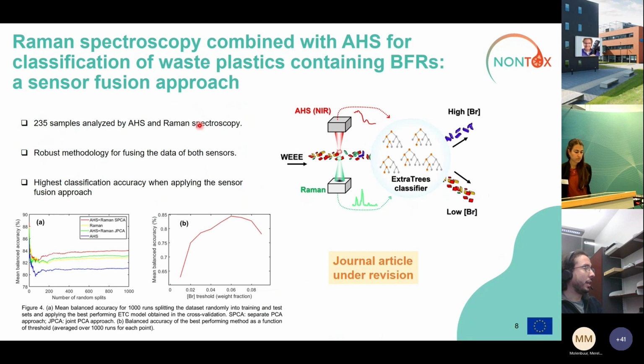In addition to that, this is a collaboration with another project where we applied two sensors. We applied AHS and a Raman spectrometer to a much broader set of samples, all sourced in this case from electronic waste. And we applied a robust methodology for fusing the data of both sensors so that we could use the information from both types of sensors to classify the plastics according to the content of bromine. Of course, bromine, but in terms of brominated flame retardants. And we showed in this work that we can get higher accuracy when we apply both sensors. This work has been submitted to a journal, and it's currently under review.